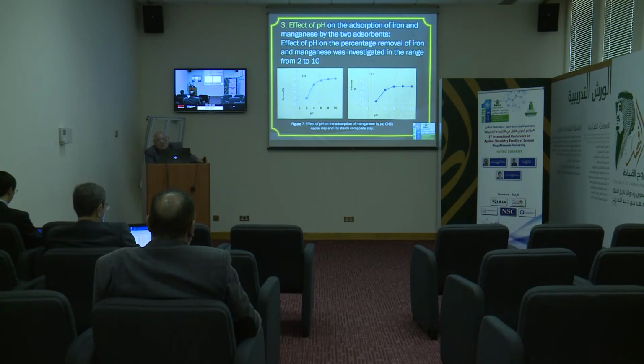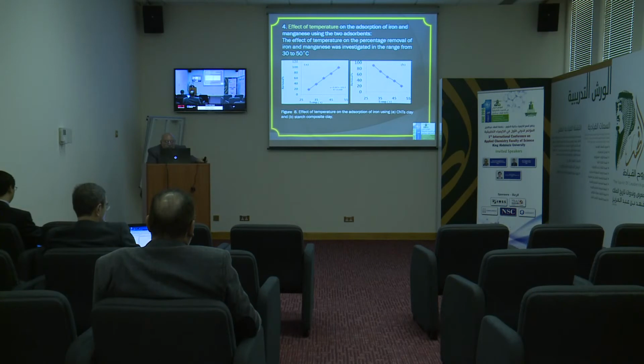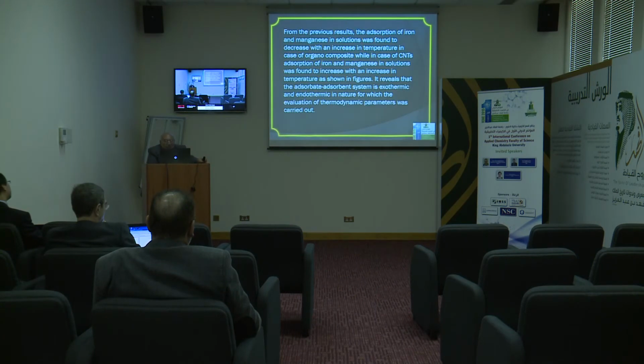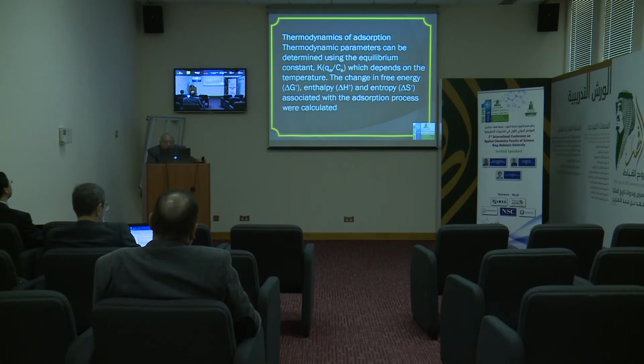Effect of the pH on the adsorption process. You see the pH range has been almost stable, almost horizontal after a pH value of 6. Effect of temperature: the adsorption of iron and manganese in solution was found to decrease with an increase in temperature in the case of the organic composite, while in the case of carbon nanotubes, adsorption of iron and manganese in solutions was found to increase with an increase in temperature, as shown in the figures.